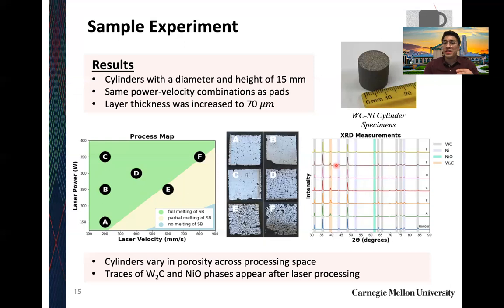If we look at another peak that's not actually in the powder either, it is a tungsten 2 carbide peak, and it's present in all our samples. And I was very confused as to why we were getting that. Turns out at very high heating rates and solidification rates, it's possible that you can induce this unstable phase and keep it there due to the very high solidification rates. And this is only present in sintering techniques or liquid sintering techniques that demand very high cooling rates or high heating rates as well.